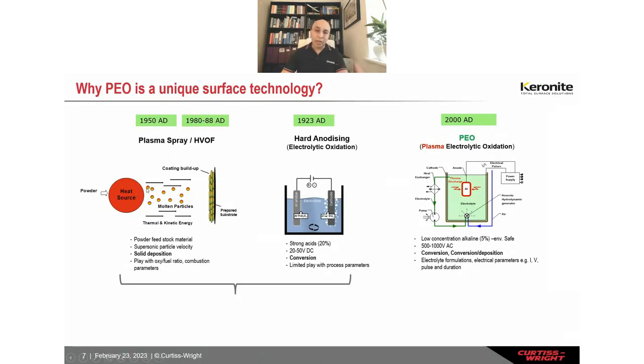You have got these solid particles, usually in powder form, 5 to 50 micron powder particles. You heat those to bring them to a molten or semi-molten state with a heat source, either using plasma or oxy-fuel combustion. And you propel them with very high velocity to deposit onto a pre-prepared substrate. And we already have some grit blasting done for mechanical keying.